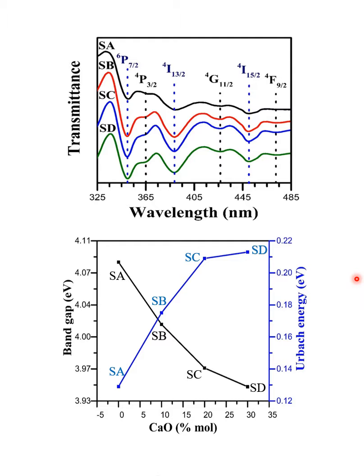The optical band gap decreased from 4 to 3.95, and the disorder in the glass structure increased with the addition of calcium oxide.